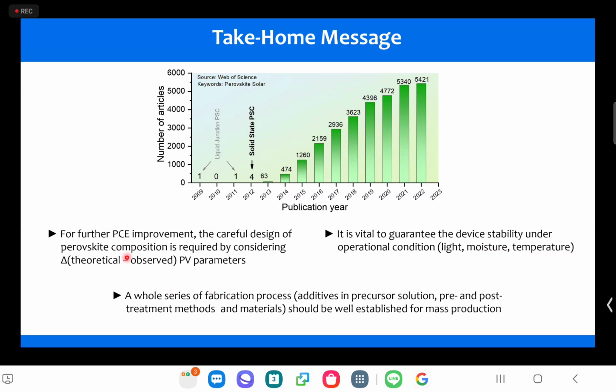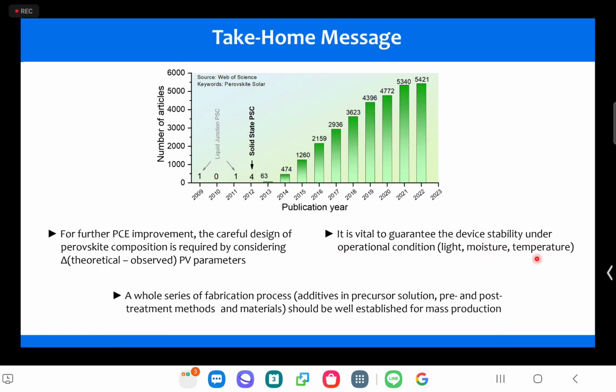However, we still need further PCE improvement. I think, as Michael previously mentioned, this material can reach or exceed gallium arsenide because of the higher absorption coefficient and the very good electron and hole diffusion length. And also we have to guarantee the device stability under operating conditions: light stability, moisture stability, or temperature stability. And also a reproducible fabrication process should be established for mass production.